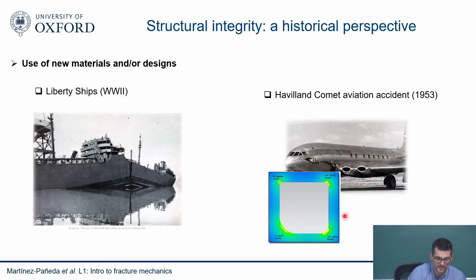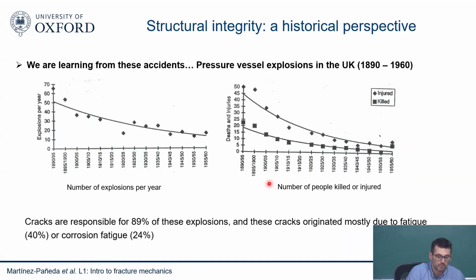This is a finite element analysis. You can see that in sharp corners you're going to get a higher stress concentration, so you're going to have higher stresses. While if you have smooth windows, then it's going to be a completely different picture. There were a few accidents, particularly this Havilland Comet accident, where fatigue cracks propagated and you lose part of the structure of the plane, and they decided to change to smooth windows. But we're learning from those things, of course, particularly the birth and growth of this discipline of fracture mechanics. Bringing fracture mechanics into standards led to a significant reduction of those accidents.